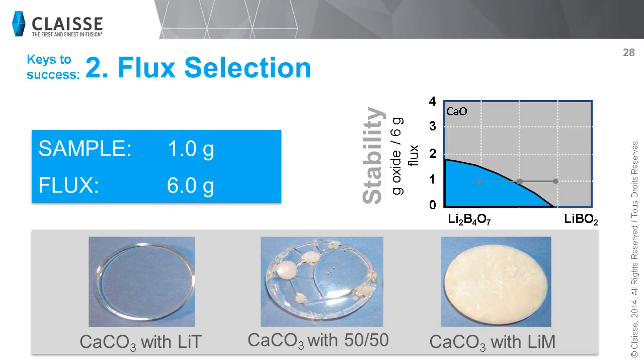In the middle, we have used a mixture of 50-50, so 50% tetraborate, 50% lithium metaborate. We obtain a disc that is cracked and that has shown some undissolved particles leading to partial crystallization. This disc can't be used for analytical purposes. Finally, on the right, the calcium sample was fused with pure lithium metaborate. You can clearly see that the disc has crystallized. It is impossible to analyze it.